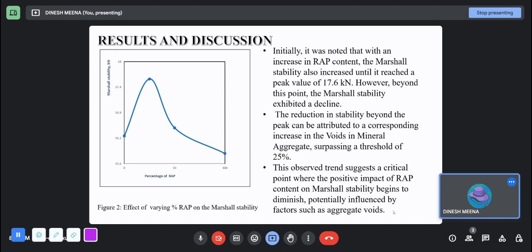Result and discussion, in which the graph shows initially it was noted that with an increase in RAP content, the Marshall stability also increased until it reached a peak value of 17.6 kilonewton. However, beyond this point, the Marshall stability exhibited a decline. The reduction in stability beyond the peak can be attributed to a corresponding increase in Voids in Mineral Aggregate surpassing the threshold of 25%. This observed trend suggests a critical point where the positive impact of recycled asphalt pavement content on Marshall stability begins to diminish, potentially influenced by factors such as aggregate voids.